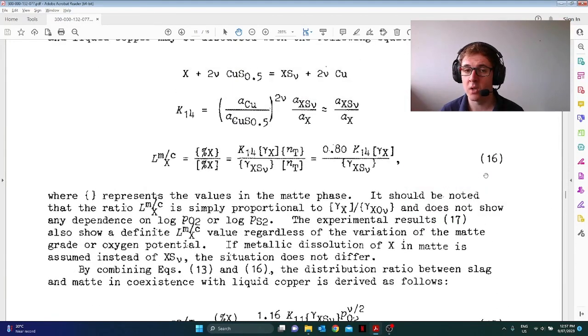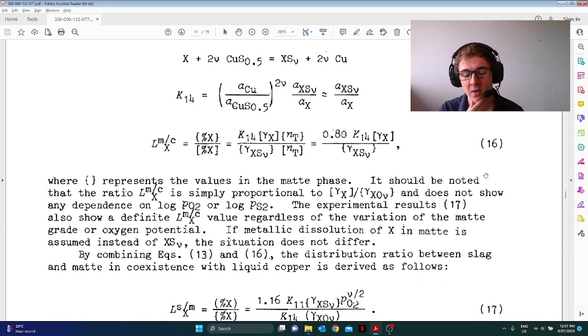it's worthwhile. So when we're looking at smelting, we control the major phases through controlling the bulk system. So your feed ratios, whether it's oxidant or reductant ratio. You control that ratio to achieve a product target. But a lot of the other components, all the minor elements, they distribute between the various molten phases depending on what they call the distribution ratio.